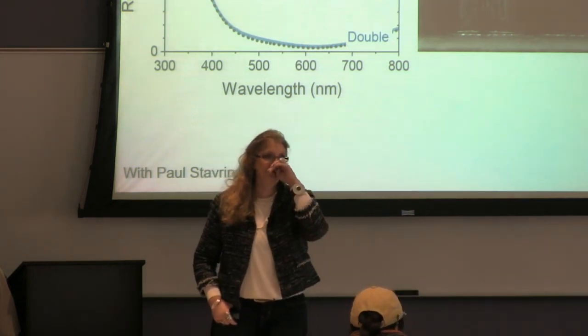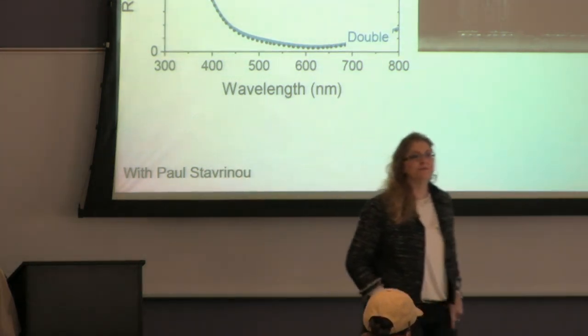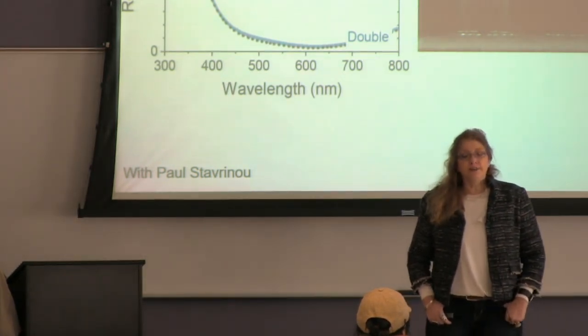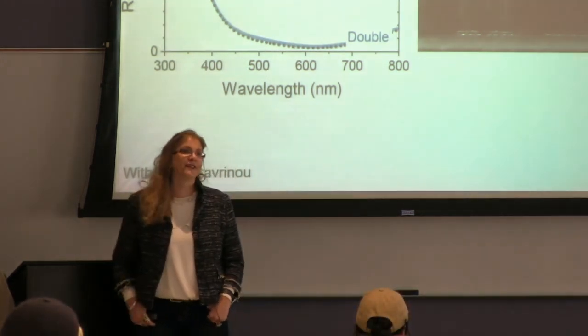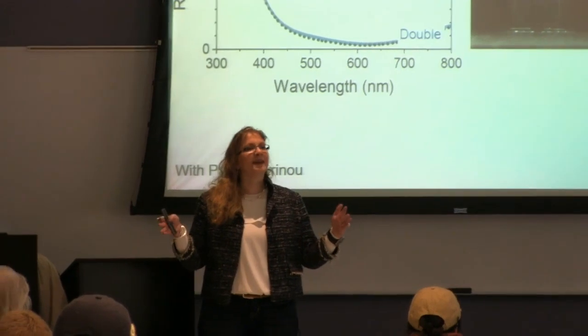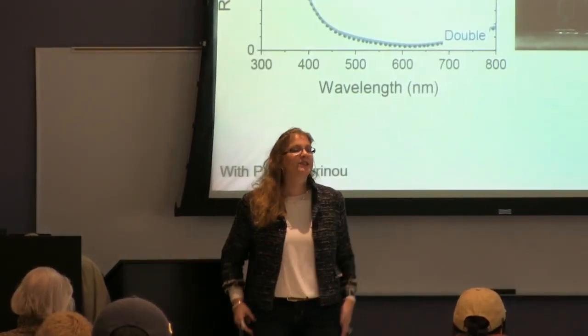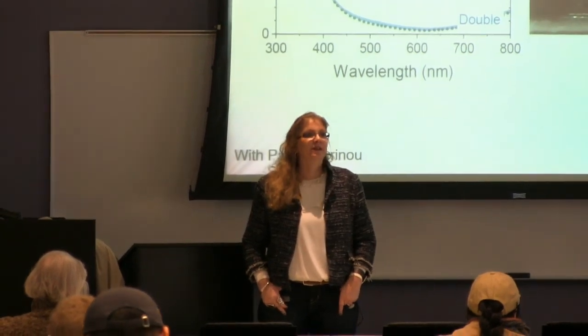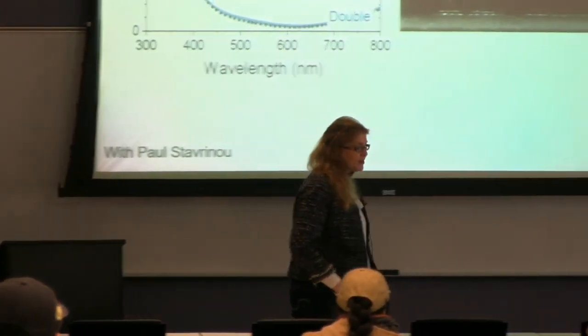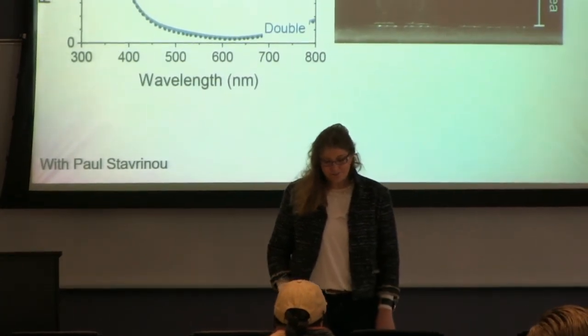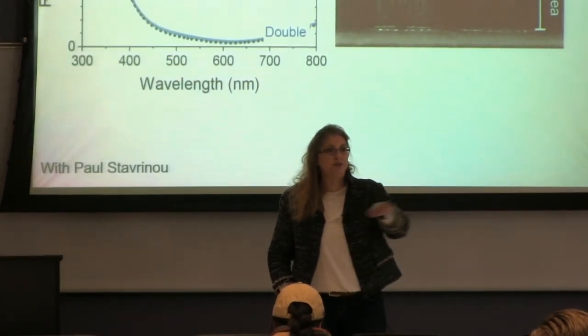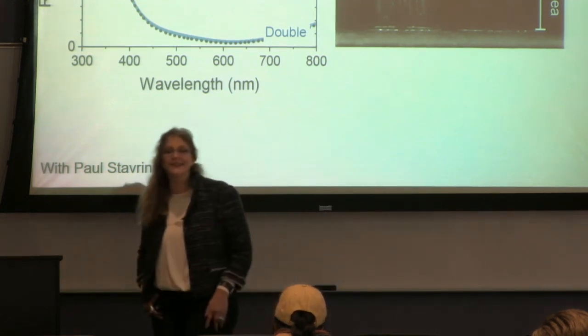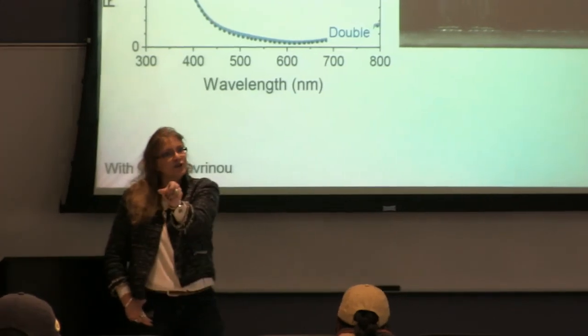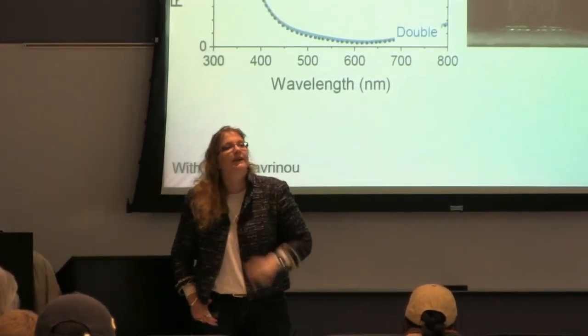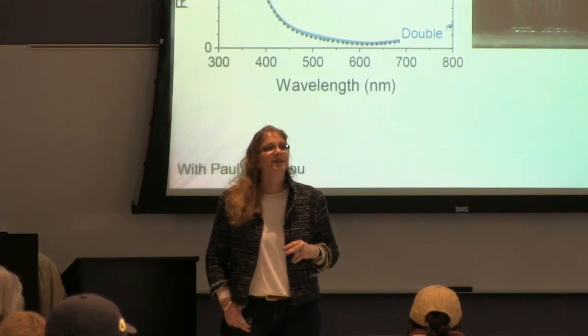If you use dipping technology to apply multiple layers, the uniformity over the overall area is very good. The only thing we have, but you will have that with nearly any coating technique, is edge effects. So actually, the thicker you make it, the better, because the central part is very homogeneous. It can actually help us, especially with some of the cavities where we want to have one side thicker, but we have not really seen, at least in the mirrors, drastic effects. So you have, like you said, at the bottom, a bit of a thicker layer, but again, that also depends on viscosity.